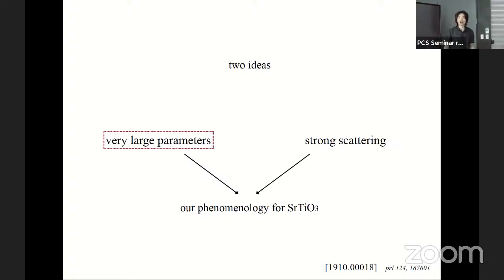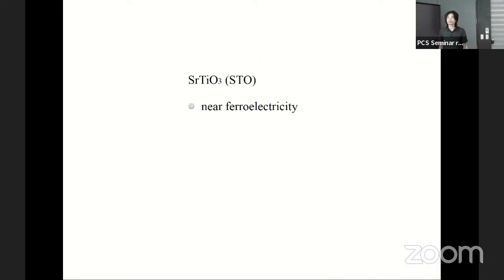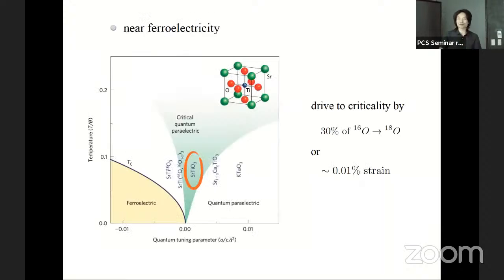So let's first look at the large parameter side of STO. The large parameter comes from the fact that one notable material property of STO is that it's near ferroelectricity. It's not ferroelectric, but it's near there. For example, you can look at a phase diagram where you have some quantum tuning parameter, such as exerting some strain on the material, or doing some isotope replacement. And just by doing some minor things, you can turn the STO from a paraelectric material to a ferroelectric material, which means it's very close to a ferroelectric transition.